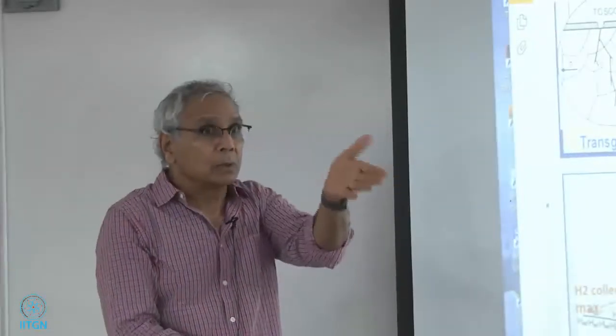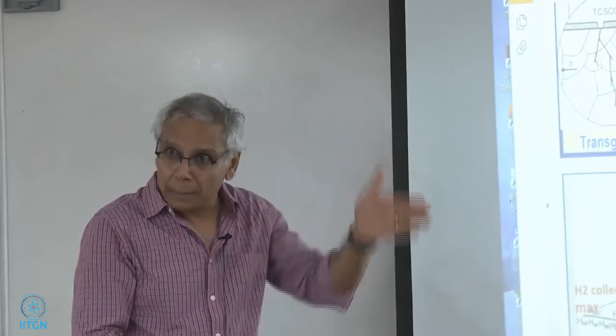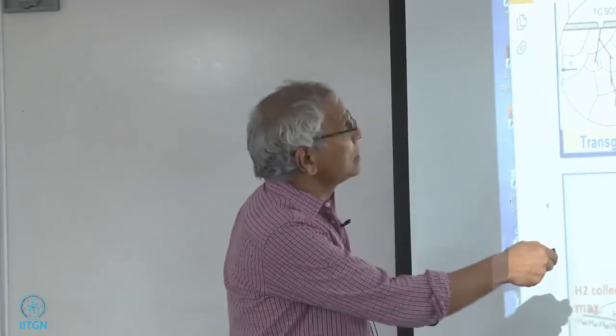So there are 2 or 3 important aspects. In stress corrosion cracking, SCC, we can have transgranular stress corrosion cracking, which is going along inside the grains. The stress axis is like this, or we can have an intergranular fracture. We can have both kinds of stress corrosion cracks. So again, you're looking at the fracture surface. It doesn't have to be a fracture surface. It's any surface that is exposed to sodium chloride solution or something, and you cut perpendicular to that surface, and you can measure the pit depths. So this is pitting. You can measure the pits, and there is a crack coming out from one of the pits.